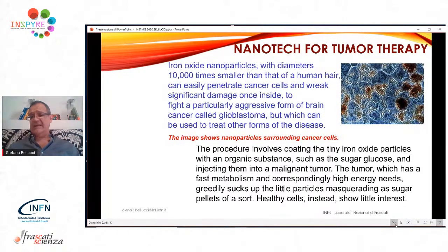How do we achieve that? There are many ways. Other ways I'm not going to mention here, just briefly, have to do with radio frequency and gold nanoparticles. But here, it's magnetic nanoparticles, actually superparamagnetic nanoparticles. Concretely, these are iron oxides, Fe2O3, in gamma phase. It's a particle that, when you apply a magnetic field, gets a magnetization. Switch off the magnetic field, the magnetization vanishes. Change the direction of the magnetic field, you change the direction of the magnetization. So easily, by introducing a magnetic field that oscillates, you can obtain an oscillating particle. In an ensemble of particles, this means increasing the temperature of the group of particles.